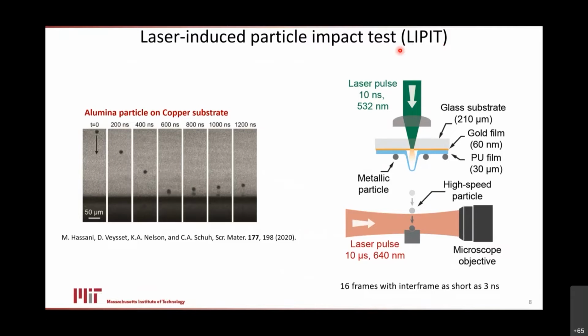And in this case, we are using a hard indenter material. So we've selected sapphire particles, alumina particles, which are spherical and very, very hard. And we're launching them to indent a copper substrate, so a soft metal. We collect a bunch of video frames, which allows us to measure the velocity of that particle as it flies in and strikes the substrate. And then we can also measure the outbound velocity. And by knowing the inbound and the outbound, of course, now we can get the kinetic energy deposited in the substrate there. And I'll just point out that the entire test here is about a microsecond in total time, so very short time scales.